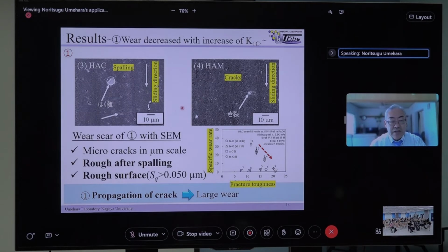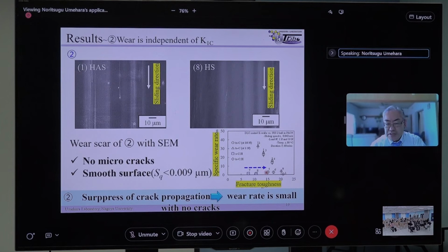We have done surface observation with SEM. In the first tendency, micro cracks on the micrometer scale were generated, and a rough surface was generated after the test. In the second tendency, there are no micro cracks, and also a smooth surface. So that's why the wear is relatively small. So there are two tendencies, which show two surface morphologies after the test.